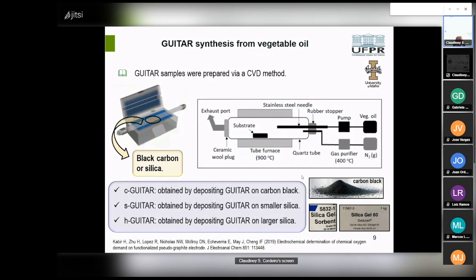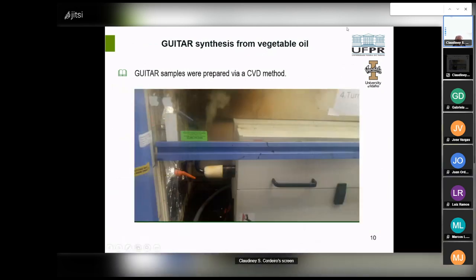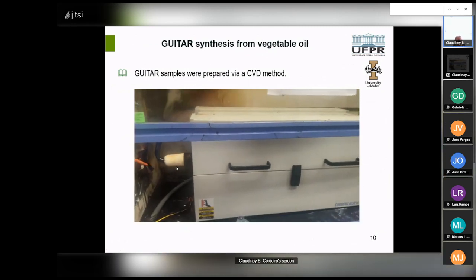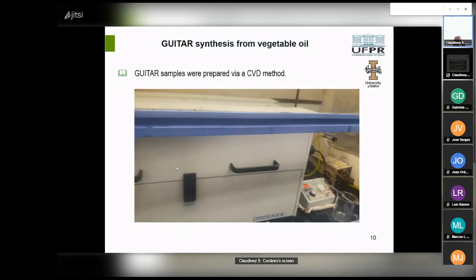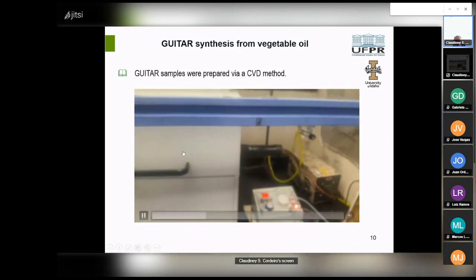This is a photo of the equipment used for GUITAR synthesis using chemical vapor deposition. 3 types of supports were used: carbon black, smaller silica, and larger silica. Vegetable oil was used as a carbon source for the synthesis. The synthesis was carried out in a nitrogen atmosphere. This is a short video of the equipment in operation during the synthesis. The synthesis time was 1 hour.